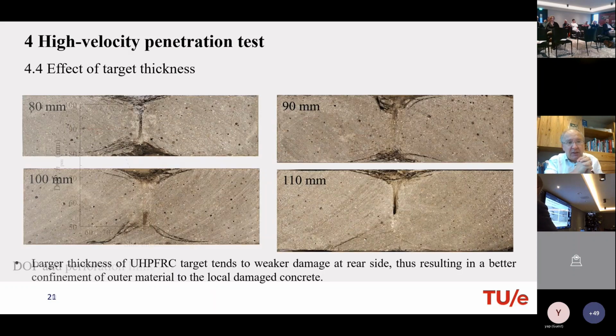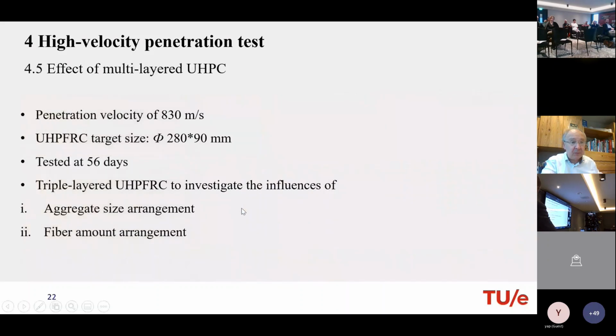Well, here you can see the effect of target thickness under the same conditions. You can see with 80 millimeter the damage, 90 millimeter, 100, and with 110, here you see no spalling at the backside already, which is very good, because this is not what you want, because then you still have damage on the inside and danger at the inside.